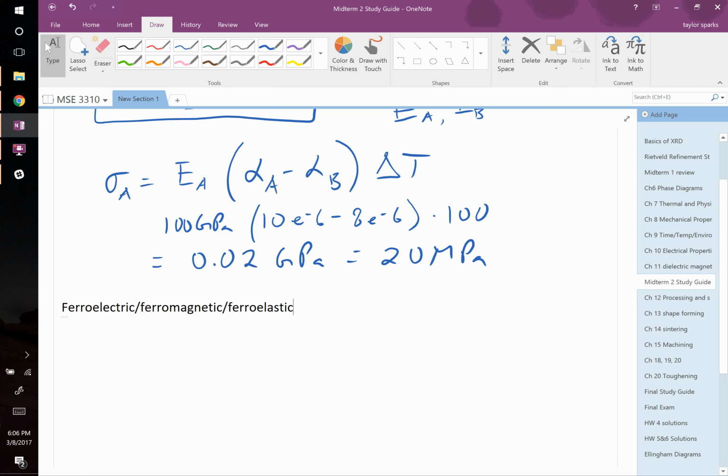You would apply an electric field to this thing as you go above the 120 degrees C, below it, right? As you do that, it's called poling. You try and make it look like a single crystal by doing that. Now, it won't ever be as good as a single crystal, but you can get pretty good at it. So you apply an electric field throughout the entire time that you have, or above the Curie temperature.